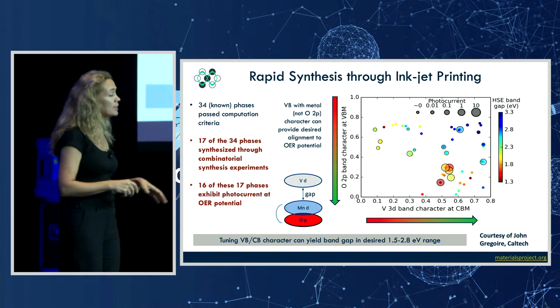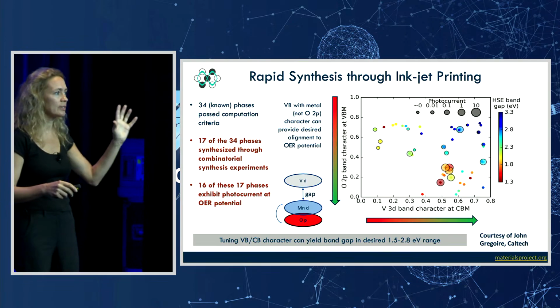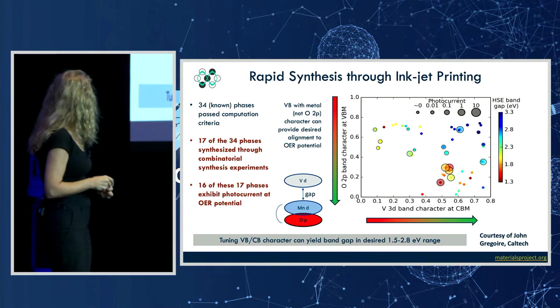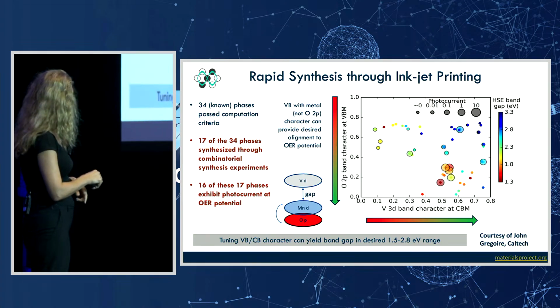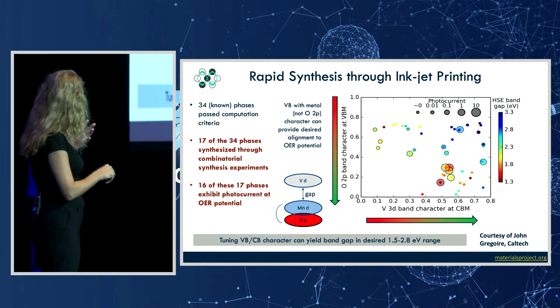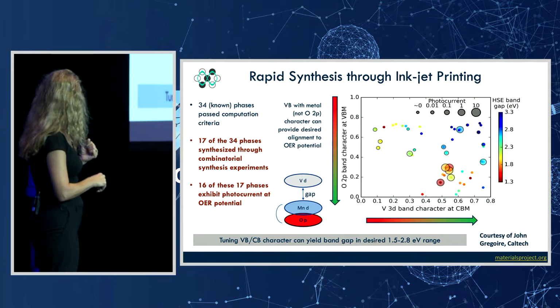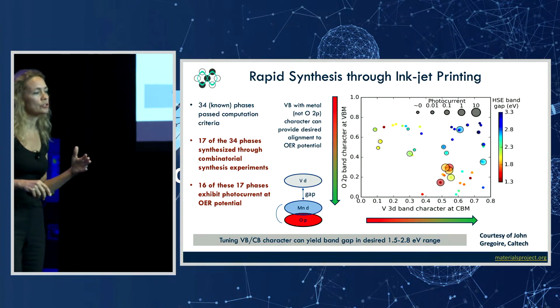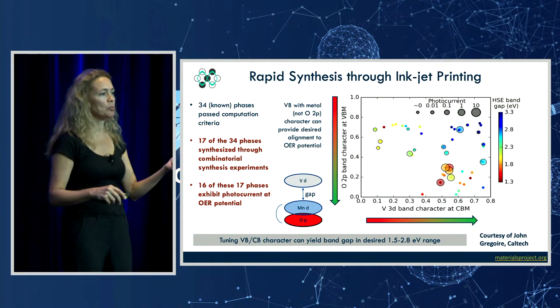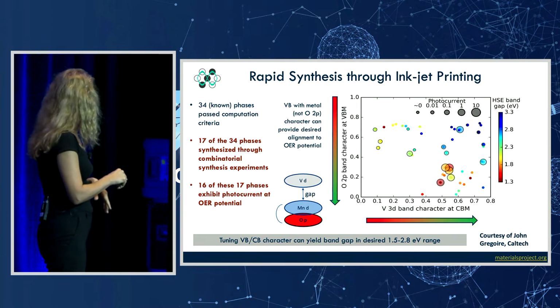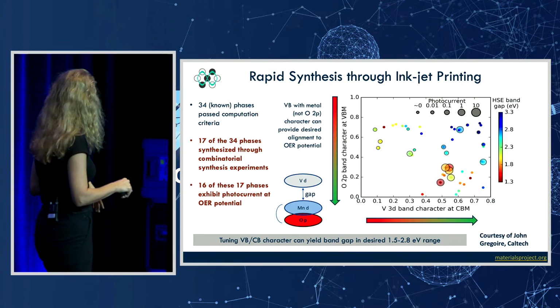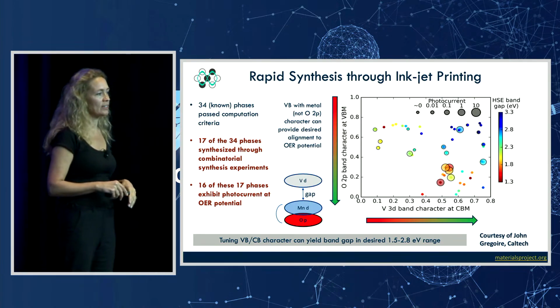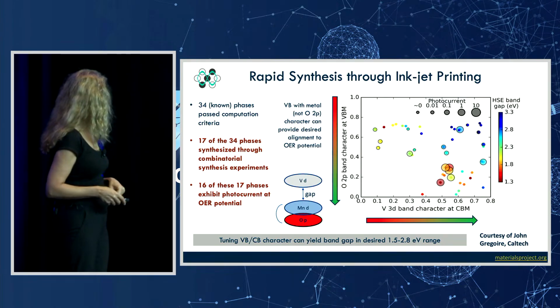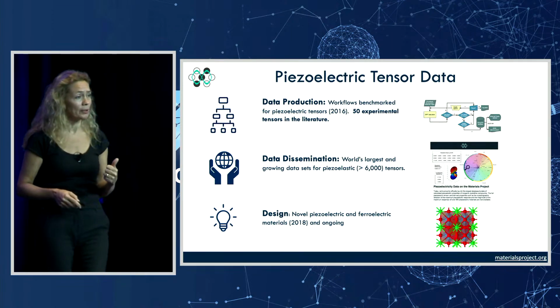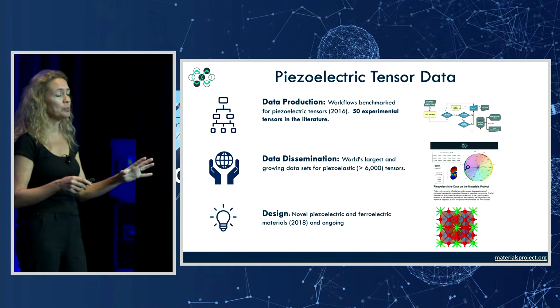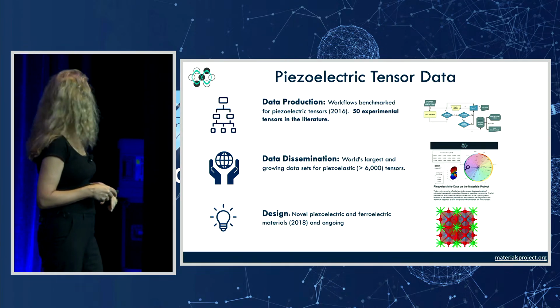But out of those, DFT had given him basically the right answer. If you were to just throw darts at the periodic table, you were unlikely to have this kind of hit rate. We also learned nicely that the photocurrent showed us that the electronic states at the valence band and the conduction band correlated with certain chemistries in this chromium, manganese, and vanadium space. Having low-lying empty vanadium D bands and not having oxygen P bands at the very top of your valence band correlated well with a good photocurrent, and we understand why. So that was the first example, and it was highly accelerated by having this nice high-throughput combi approach, being able to make all these materials, or at least a good chunk of them, in one shot.